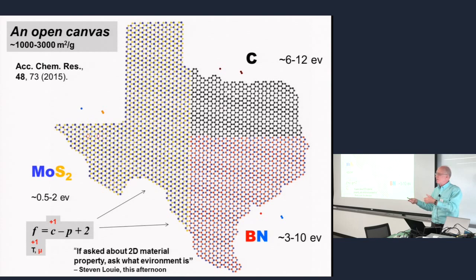So thermodynamics of a gas phase can control the composition of defects here and the composition of edges, type of edges, and even shape of crystal. That's because it's so open, ideally from both sides, but if it's on substrate, at least on one side. The energy of doing it, of course, the barriers and energies are pretty high, much lower in case of TMD. You see, just to show you scale. These are very rigid lattice. This one is polyelemental, but still very costly to move atoms around depending on which combination. But these are much softer, especially sulfur vacancies are known to be formed very easily, and that's what makes them a little bit volatile.